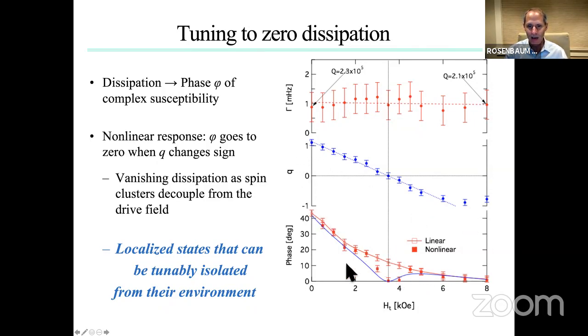And down here, I'm looking at the phase. The phase is the ratio of the imaginary to the real part of the susceptibility. So when the imaginary part of the susceptibility goes to 0, phi goes to 0. And what you see is, if you look at the linear response, it varies smoothly. That's the red here. But if you look at the nonlinear response, in fact, the dissipation goes to 0 just where the Fano parameter crosses 0.